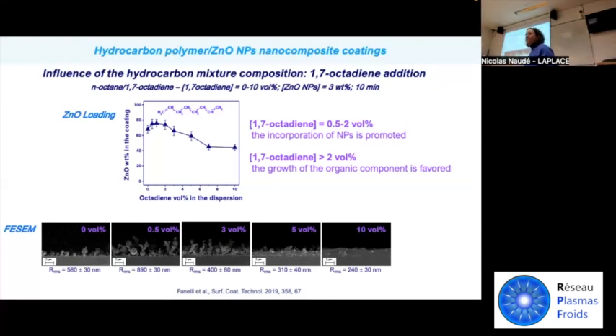Why an inorganic layer? An organic layer will be attacked during photocatalysis, but it is easily processable, and the inorganic material withstands the process very well. There is no dissolution of the matrix, because you can imagine using a polar matrix, SiOx, all these things. Will it be stable in water? Not during photocatalysis. Stable in water, and then what happens during operation, and then what happens in various reactions with radicals, oxygen species, and so on. So there is always a balance.